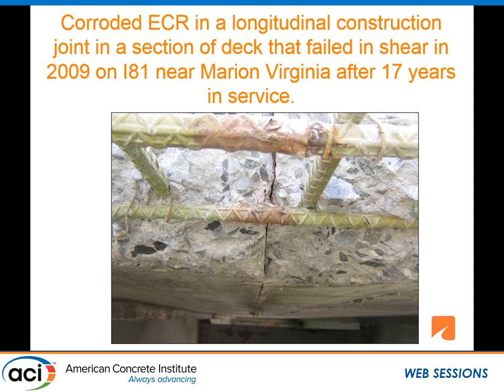And the typical way to do deck replacement now is not to close the bridge, but to close half the bridge. Replace one half of the deck, put traffic on the new concrete, and then replace the other half. And so you end up with one or two longitudinal construction joints because of the way we replace these decks. And this is just one of those. This deck failed in shear in the left wheel path of the travel lane after only 17 years in service. And you can see the picture there of the leaking construction joint.